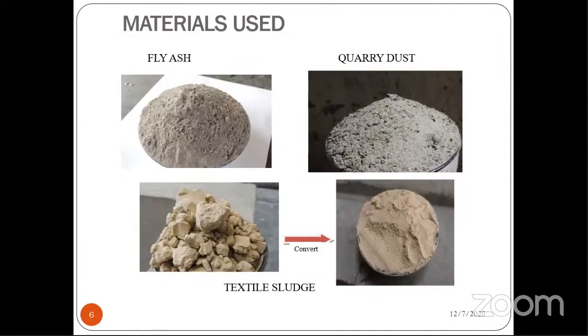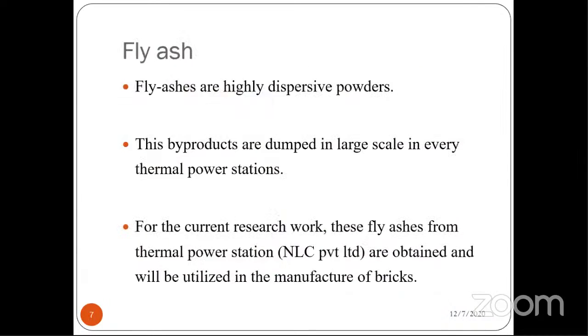These are the materials we use: fly ash, quarry dust, and textile sludge. We converted the textile sludge into powder form. Let's take the first one, fly ash. Fly ash is a highly dispersive powder. These byproducts are dumped on a large scale in every thermal power station. For the current research work, this fly ash from a thermal power station is obtained and will be utilized in the manufacture of bricks. Fly ash particles are generally spherical, and these small glass spheres improve the fluidity and workability.